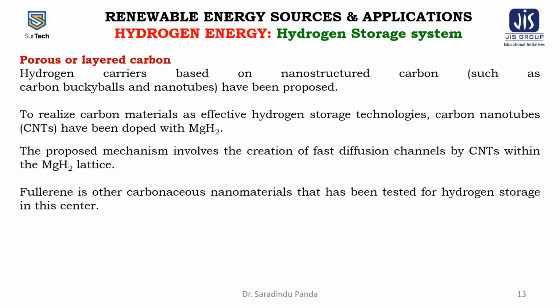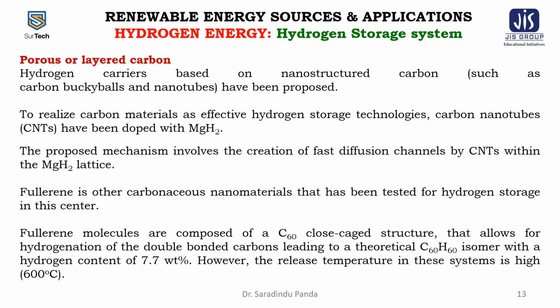Fullerene is another carbonaceous nanomaterial that has been tested for hydrogen storage. Fullerene molecules are composed of a C60 closed cage structure that allows for the hydrogenation of the double bonded carbons, leading to a theoretical C60H60 isomer with a hydrogen content of 7.7 weight percentage. However, the release temperature in these systems is very high, about 600 degrees centigrade.